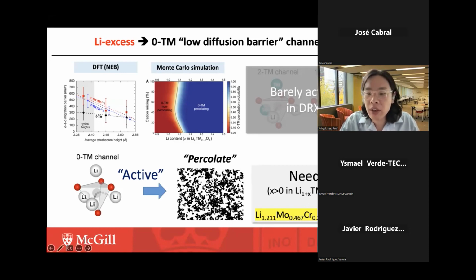Right here there is extra lithium over the transition metal, so there is much more lithium than transition metal. We call it lithium excess, and we found that if these DRX materials are made into lithium-excess composition, then these 0-TM channels start to percolate, so this material can become a very high capacity material. And this basically explained why this lithium chromium oxide could deliver high capacity,